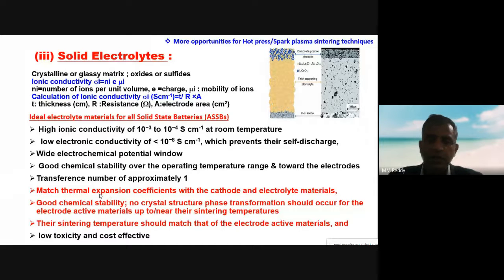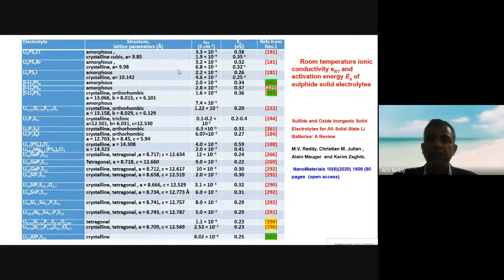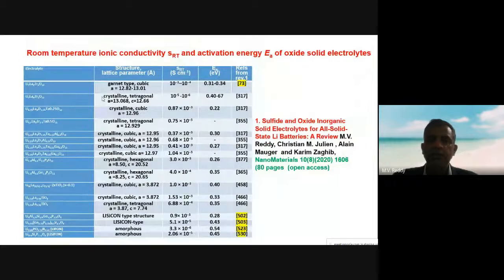So it is very important that the thermal expansion coefficient has to match with both cathode and electrolyte, with good chemical stability, and no crystal structure transformation should occur near the sintering temperature. These are very important points here too, and conductivity also has to be reasonable, meaning 10 to the minus 3 Siemens per centimeter is good for applications. You see different types of sulfides, different compounds, and oxide based garnet electrolyte. Each electrolyte has advantages and disadvantages in terms of processing, etc.